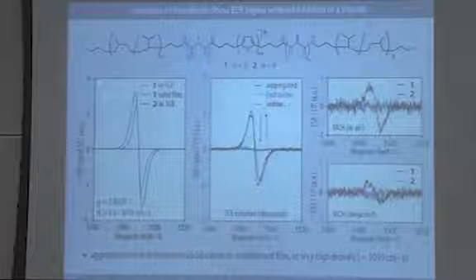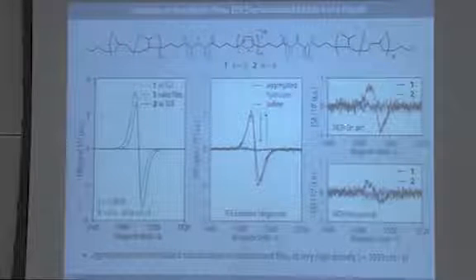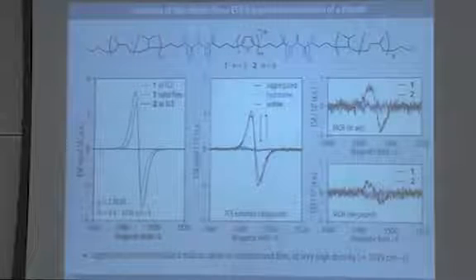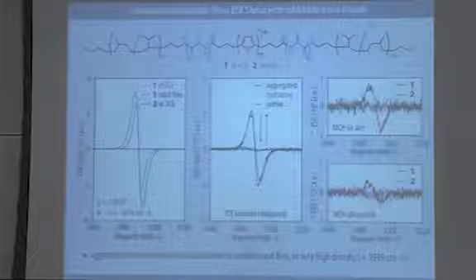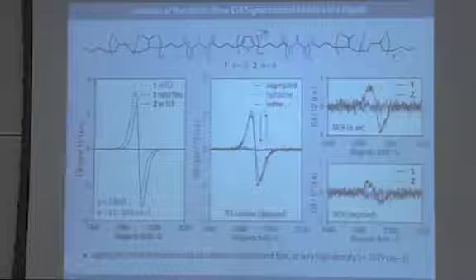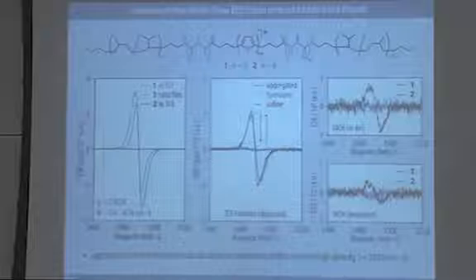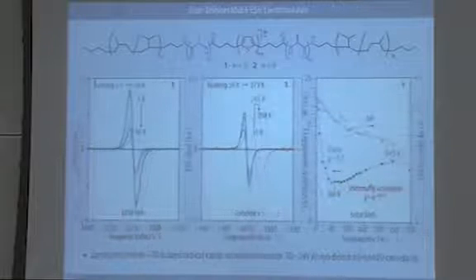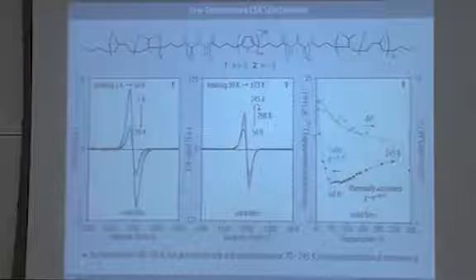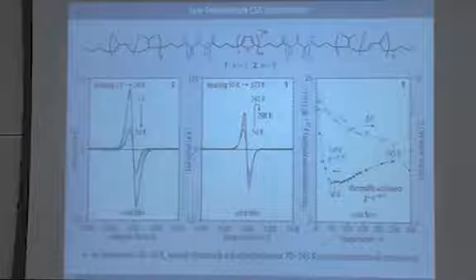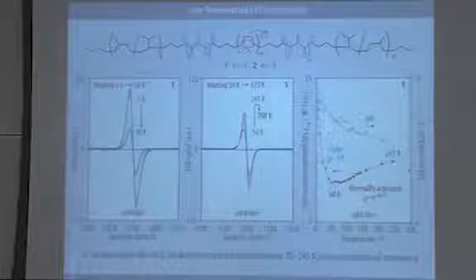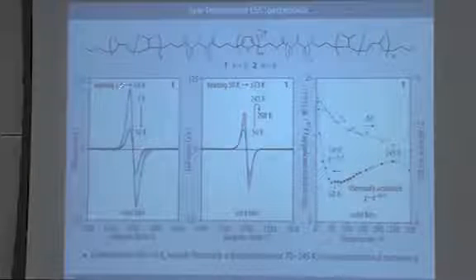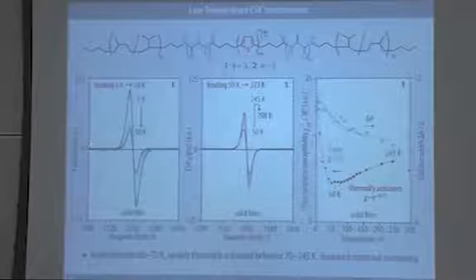reformed by adding an oxidant. We tried to exclude the role of the chlorinated solvent by going to methylcyclohexane, but we also observed the signal in the solid film. So we're pretty sure it's actually an inherent feature and not a result of some oxidation process, not even involving the chlorinated solvent. As we did the ESR spectroscopy in solid films, temperature dependent, you see the original spectra here,